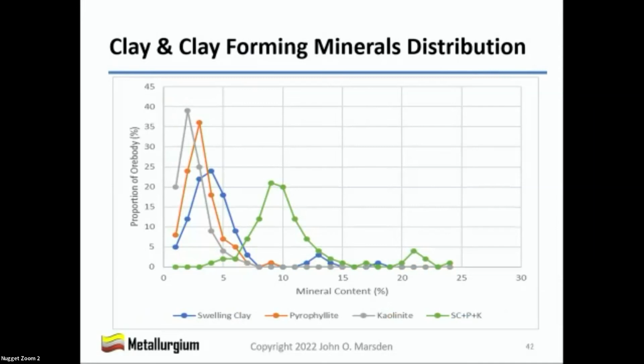And you can see here, the swelling clay is the blue curve, the pyrophyllite is the orange or brown curve, the kaolinite is the gray line. And when he summed those percentages, he got the green curve, and it showed a bimodal distribution. And 10% of the samples contained over 20% of the swelling clay plus pyrophyllite plus kaolinite. So with this information, he put together the following table.